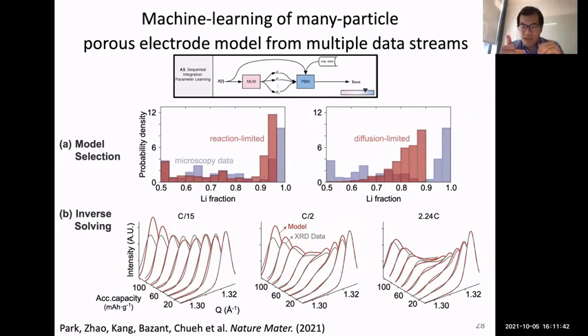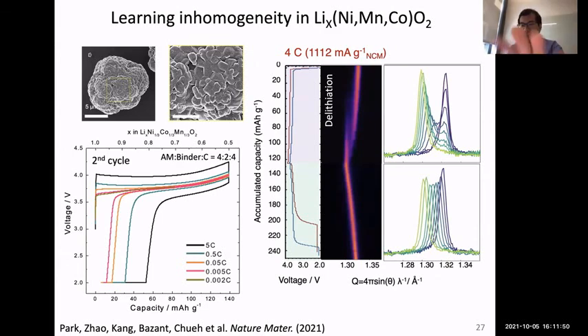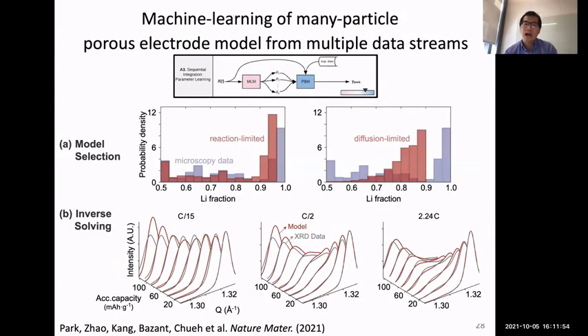But what we aim to see is how lithium is distributed. So what we have done here is take this X-ray diffraction data, which has no spatial resolution, and combine it with a snapshot, high resolution image that does not have time resolution. And we merged the two using a machine learning method. Here we're doing what's called sequential learning, whereby we first do machine learning and then follow up with a physics-based model. Again, without going through details, we have taken the images and the diffraction patterns, and essentially simulated what kind of heterogeneity can properly explain this data. We merge the images with the X-ray diffractions. So this is essentially trying to learn the heterogeneity from multiple data streams.